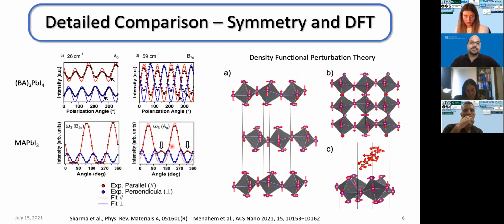Now we've asked our collaborators to also perform density functional perturbation theory and calculate the atomic displacements of the modes. And when we compared the already compared modes and compared their atomic displacements, we saw a great match between the modes. As you can see here, as an example, one mode of butyl ammonium lead iodide and its comparable mode in methyl ammonium lead iodide exhibit a very similar atomic displacement. And here in figure C, you can see the large contribution of the butyl ammonium to that motion, which tells us that not only the frequencies, but the symmetries and the atomic displacements in both materials are very similar.